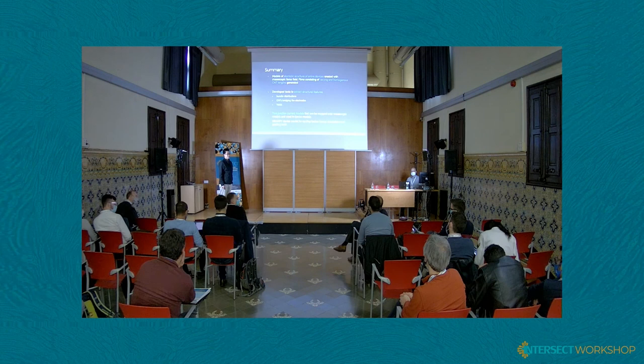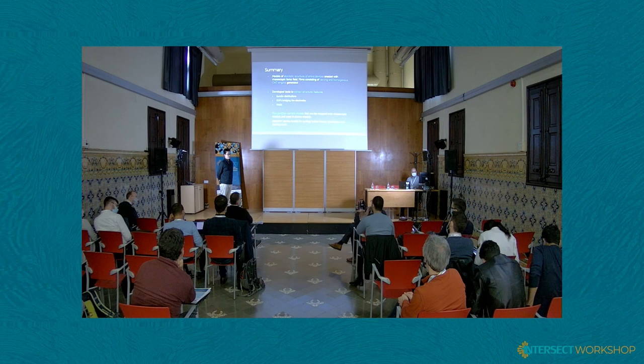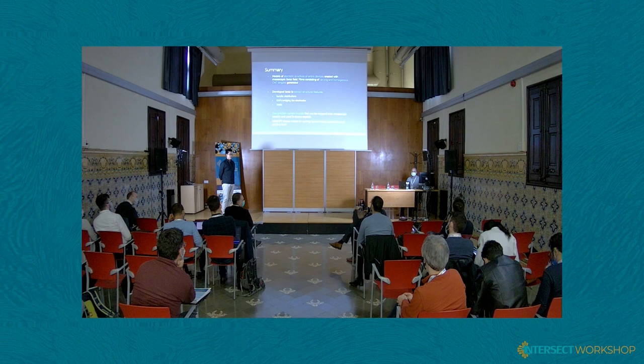This is not really what you see when you look at TEM images of real samples. So maybe that has to do with the way that you model the bundling or the structures, with these continuous models of the nanotubes as continuous rods. So maybe when you deposit them experimentally, you have defects, or maybe you have even the corrugation of the energy that you show in one of the last slides that precludes the nanotubes from sliding and finding the minimum energy structure, which is fully aligned. So I wonder if you can comment on that, if you think that your models are realistic or you're missing something.